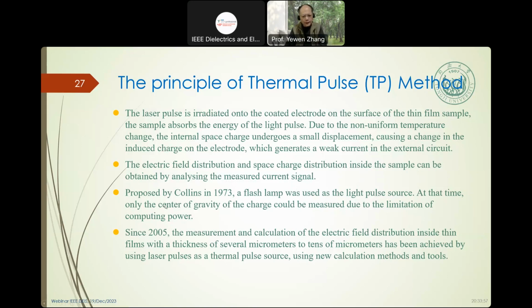This method was proposed by Collins in 1973, when I was very young. He used a flash lamp. At this age, the laser was not very popular in the laboratory, so he used the flash lamp as a thermal pulse source. At this time, only the center of gravity of the charge could be measured due to the limitation of computation power. Since 2005, the measurement and calculation of the electrical field inside a thin film with a thickness of several micrometers to 10 micrometers has been achieved by using a laser pulse as the thermal pulse source, with new calculation methods and tools.